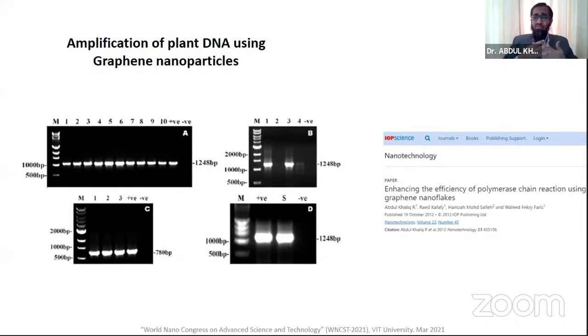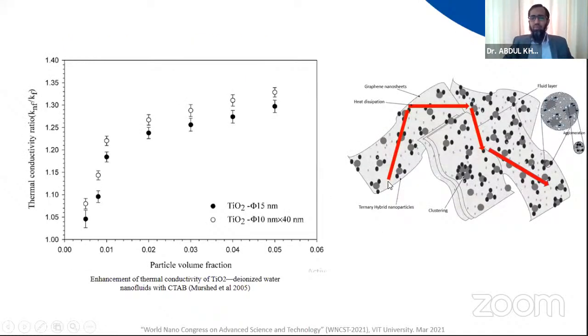Similar results can be found in those papers, whereby there are actually hundreds and thousands of papers on nanofluids, where it has been established that as you increase the concentration of nanoparticles in fluid, the conductivity will increase only until a particular point. Further increase in concentration will lead to sedimentation, and as a result the conductivity will go down. This can be corroborated very clearly in this result, and this paper was published in 2012. Then we proposed a mechanism as to why the enhanced conductivity effect will be more prominent, or could be more prominent, than any other biomechanisms proposed by our counterparts in the biofield.